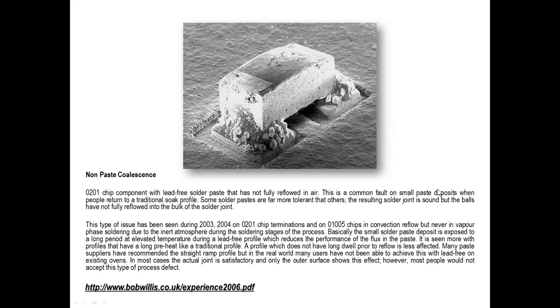Right, so moving on to a few more reflow soldering defects. Something that back right at the start of lead-free technology, we saw at the lead-free experience that we ran with a smart group: this is non-coalescence of solder paste, where you've got solder paste with spots or warts. That's what I used to call it, spotting or warting. When the US started to get into lead-free technology and also trying to have straight ramp profiles with very small paste deposits, they came up with the term graping. And I think graping is a good term.